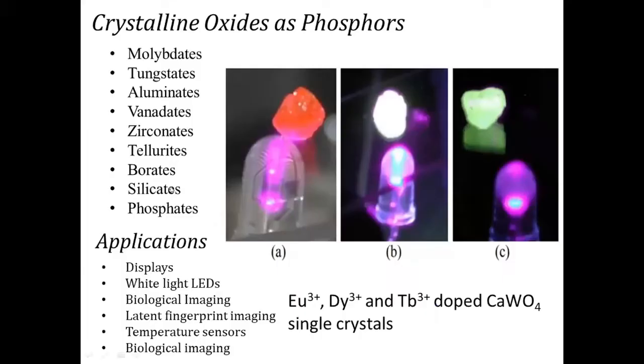So in the second part, I come to the crystalline oxides, which can be used for phosphors. So far, we have been discussing the glasses. Glasses are non-crystalline materials, and they are metastable materials. If you heat a glass above its glass transition temperature, it will crystallize. Whereas the crystalline materials are stable. They are stable up to 1000 degrees Celsius. But the glasses are not stable. If you heat a glass, it will crystallize or it will gradually melt.